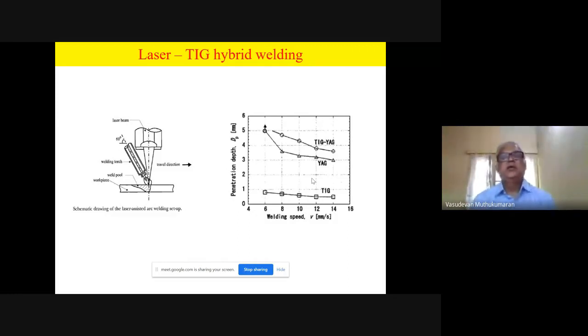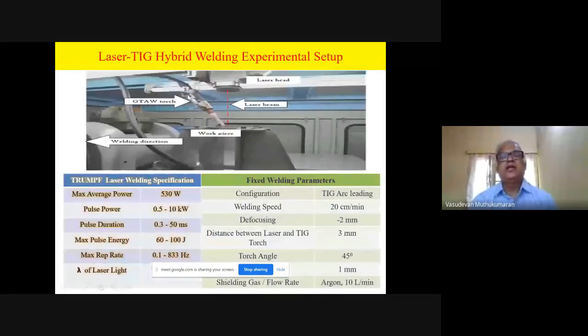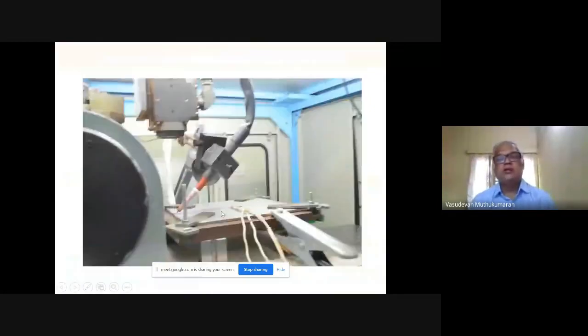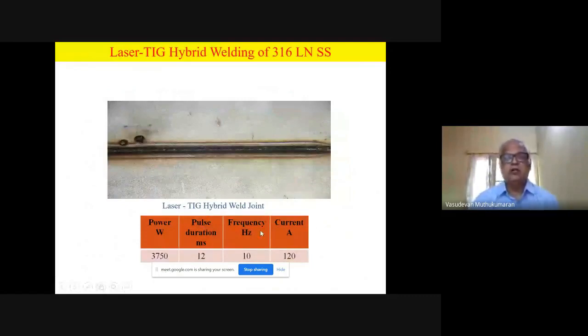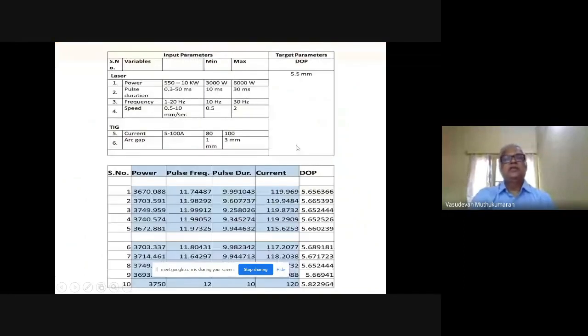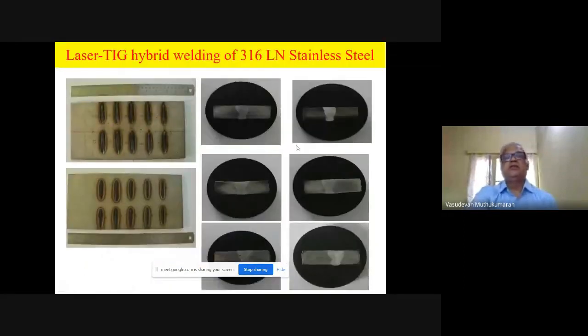Here you can see the TIG torch positioned at an angle, integrated with the laser gun. These are the parameters we used. You can see a closer look again. This is our 6 mm thick stainless steel plate, 300 mm long. We are doing square butt joints. You can see the positions. We successfully welded again using the parameters given here: pulse power, pulse duration, frequency, current on. We optimized to get a defect-free joint. You can see the weld cross section, full penetration.